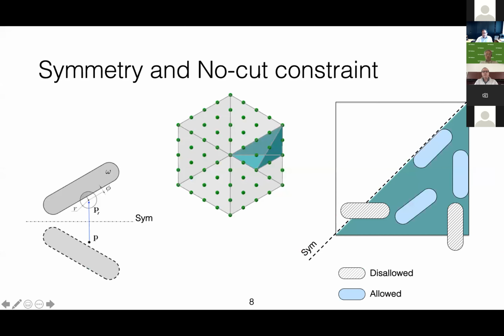We also impose in our method symmetry and what we call no-cut constraints. The symmetries are so that we obtain desired material symmetries for the effective properties of the lattice. So in this particular example, say we want to have cubic symmetry. And so you have 9 planes of symmetry, which give you this reference region, which is a tetrahedron. And the way we accommodate symmetry is fairly simple: we just reflect the points at which we compute the projected density with respect to the symmetry planes.